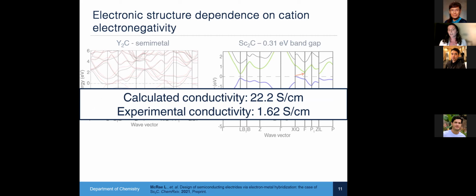And so we took the band structure and calculated the conductivity at room temperature and got it to be 22 Siemens per centimeter. And then our experimental conductivity at room temperature is about an order of magnitude lower than that, meaning it is still characteristic of a semiconductor, and it's expected that our experimental value would be slightly lower, given that the ideal crystal structure that we have calculated computationally doesn't include impurities or grain boundaries. And so this indicates that our experimental structure is semiconducting, and we have in fact made the first semiconducting 2D electride.